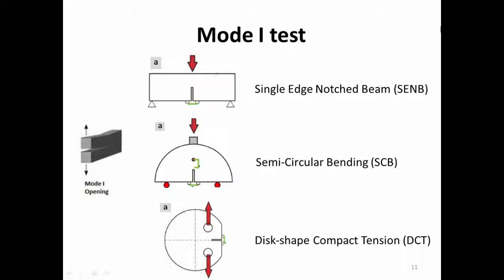Right? The second one is called the semicircular bending. Instead of using this rectangular one, they use this semicircular one, and they also put a notch here. The crack will also grow in this direction. And the third one has this shape, and they carve a notch, and there are two holes here. They just pull apart these two holes, and the crack can also grow along this one.